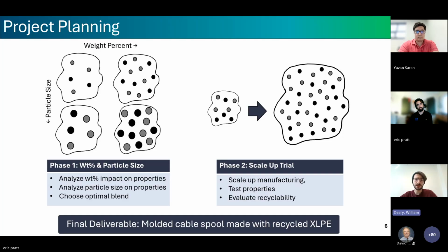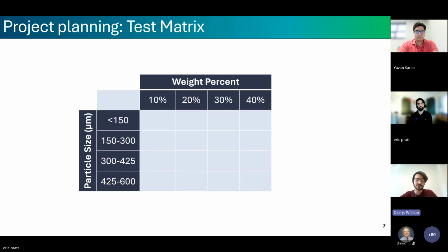So since both particle size and cross-linked polyethylene loading were expected to affect our blend's behavior, we built an experimental matrix of 4 different cross-linked polyethylene weight percents, which were 10, 20, 30, and 40, and we crossed that with 4 different particle size ranges, ranging from under 150 microns up to 600 microns. This gave us 16 distinct formulations to evaluate.